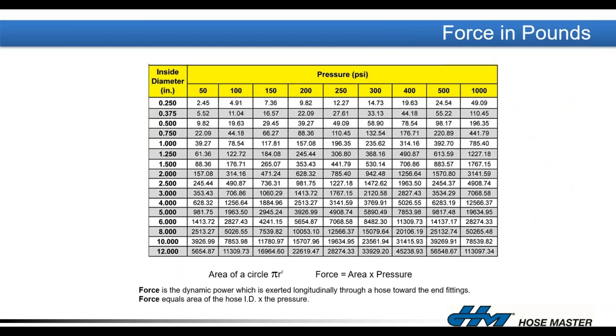So if you have a 4-inch inside diameter metal hose that's being used at a pressure of 150 PSI working pressure, remember, that corrugated tube is trying to stretch back out to elongate back into the tube that it was formed from. And the braid and the fitting and welded attachments are what prevent that metal hose from elongating because of that Chinese finger trap effect we just discussed.